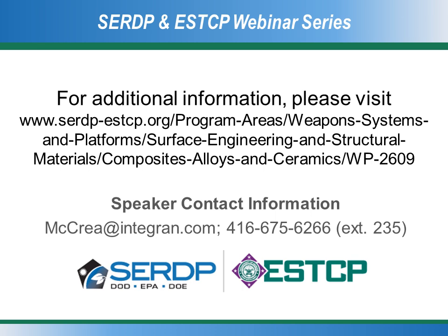That, in that specific use, there's actually a very definite, very significant improvement in the lifetime of the product. So you can easily put it on the hydraulic cylinders, and you get improved performance compared to chrome, specifically when you have that high chloride corrosion present. Thank you. A question from Boeing.